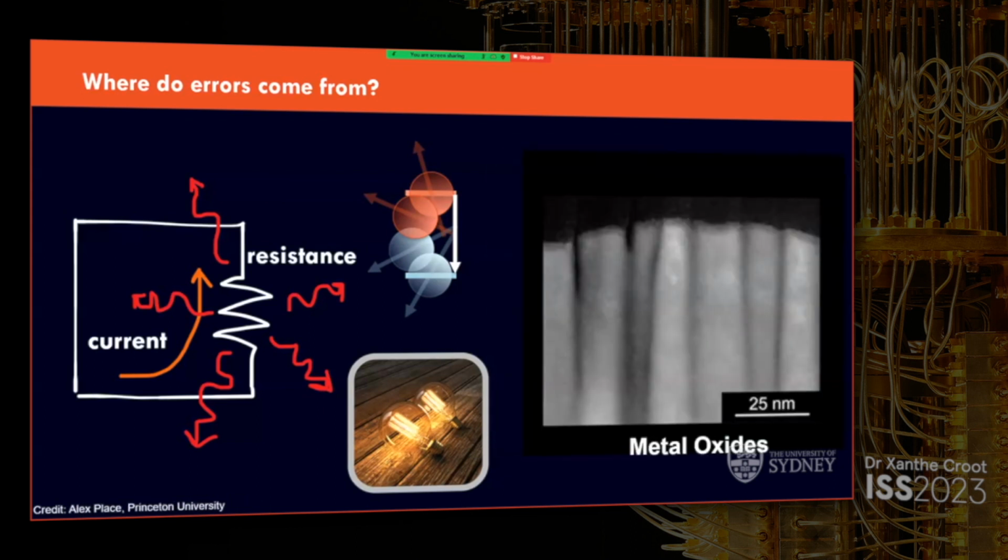This is an image of some metal in a transmon qubit. And any metal has a really thin layer of oxide on the top. So when this circuit becomes superconducting, all this metal will superconduct, but there's going to be a layer of oxide at the surface that is actually quite resistive and can still dissipate that quantum information. And that's a real challenge.